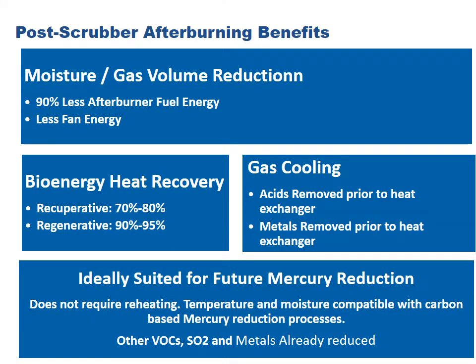We can recover the heat, a regenerative 90-95%. You could actually do natural gas injection and bring that up to like 97. Remarkable. The ceramic media goes from 100 to 1,000 degrees and back again in 90 seconds, 24 hours a day, 7 days a week. The ceramic is similar material that they use on a space shuttle, the tiles to protect. So it was really NASA who developed the materials that made this whole thing possible.